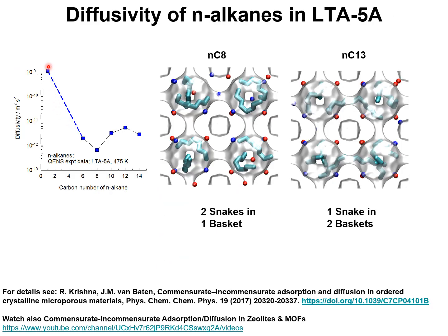We now examine the quasi-elastic neutron scattering experimental data on the diffusivities of normal alkanes in LTA5A zeolite. LTA stands for Linde Type A. What's interesting to note is the diffusivity varies in a non-monotonic manner with increasing chain length.